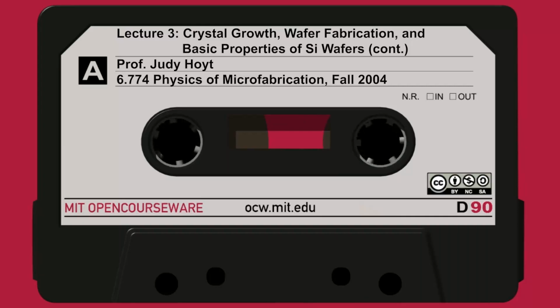And the way to estimate them is a little bit of a circular argument, but it's going to come out in this course by fitting impurity diffusion data. In other words, people hypothesize that the diffusivity of a dopant requires the existence of certain vacancies. And then they see diffusivities increasing and decreasing according to temperature or charge states. They say, oh, the concentration of vacancies must be going up by this much. So people measure diffusivities and infer concentration of point defects. It's a little bit circular, but that's how a lot of people have estimated these things. So don't expect to find anywhere in the literature some perfect equation. There's a lot of controversy, but there's some agreement these days that these are rough numbers.